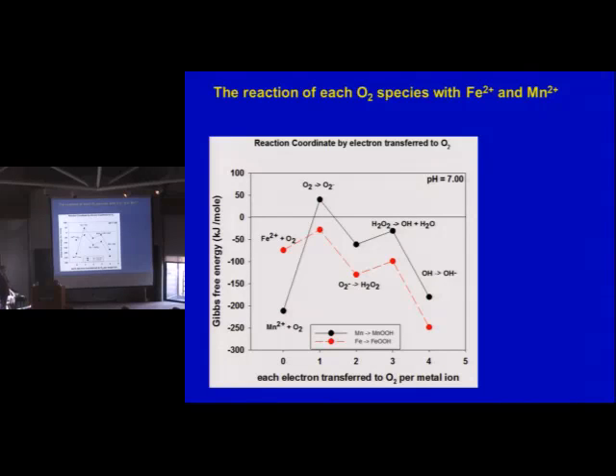So here's another way to represent it. This is now the Gibbs free energy versus the number of electrons transferred. So if I looked at the free energies of the free species, the hexaaqua iron and oxygen, and manganese 2 and oxygen, I would have the sum of those free energies, and it would be here. If I now look at the first electron transfer step with oxygen going to superoxide and the iron 2 going to iron 3 or the manganese 2 going to manganese 3, you notice that manganese is unfavorable by a substantial amount. So that's what's going on.